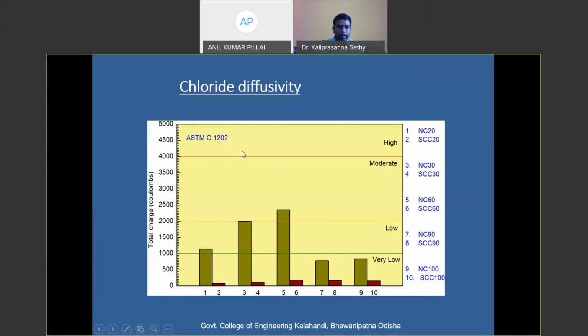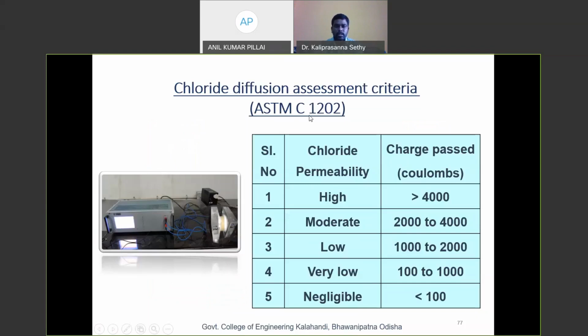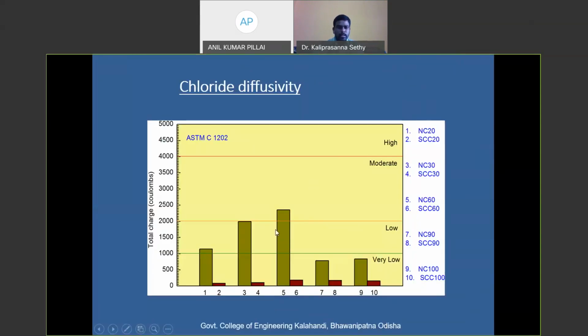And here are the results plotted as a bar chart, and you can see the maximum chloride diffusivity values in coulombs is around 2000 to 2500. As per the ASTM standard, if it ranges between 100 to 1000 coulombs, the chloride permeability is very low, and 1000 to 2000 is low. So from this you can see it is falling under this low to very low category.